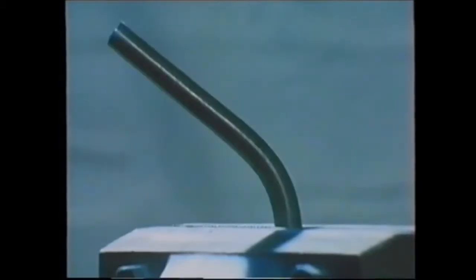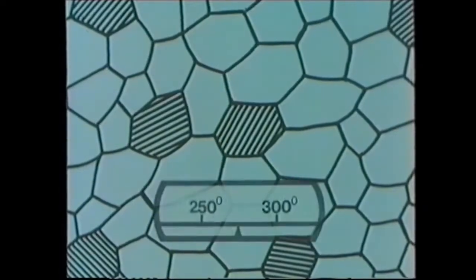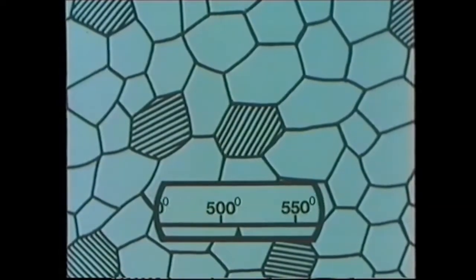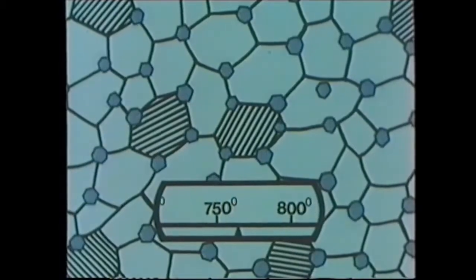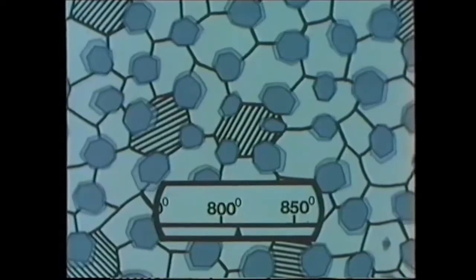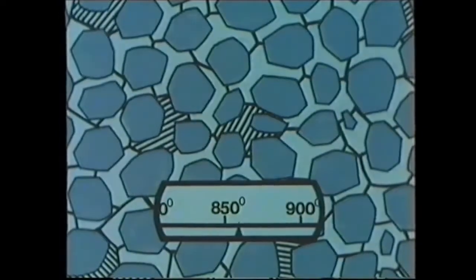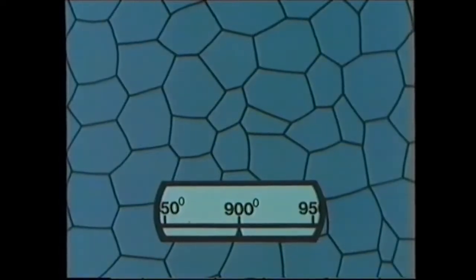So far, we've only looked at the heat treatment of 0.8% carbon steel. What happens if we try to harden steel containing 0.1% carbon? Here, the grains are mainly iron. Again, nothing happens until the temperature reaches about 720 degrees centigrade. And once again, the new grains begin to form until they completely take over the old grain structure. In this case, we have to take the temperature up much higher to nearly 900 degrees centigrade. If we quench it now, there's insufficient carbon for the hard, needle-like structure to form. We've finished up exactly as we started.